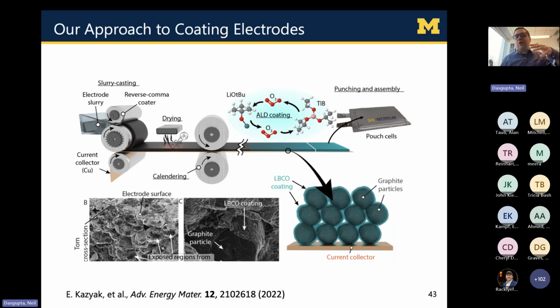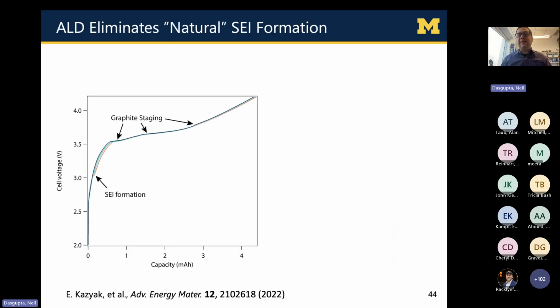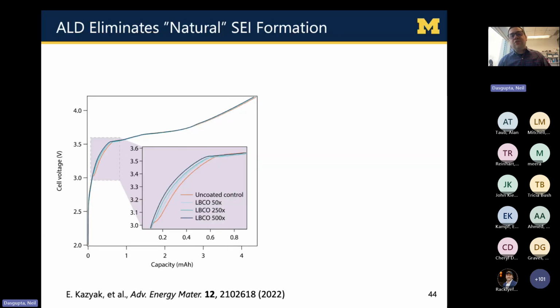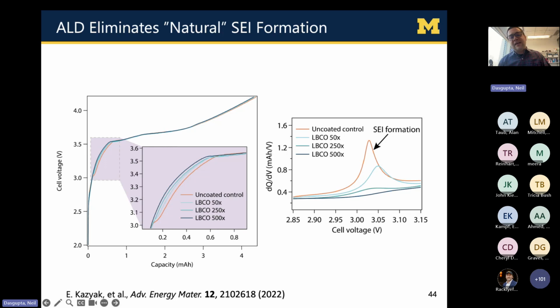We do electrode level coatings and assemble pouch cells in the battery lab. What we did was then we looked at that first formation cycle where the SEI layer is known to form. And if you zoom in on the voltage trace, there's this little bump that occurs between 3 to 3.5 volts in the first formation cycle. This is the well-known signature of SEI formation.